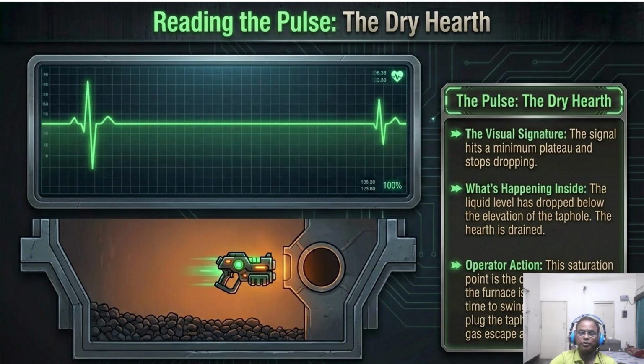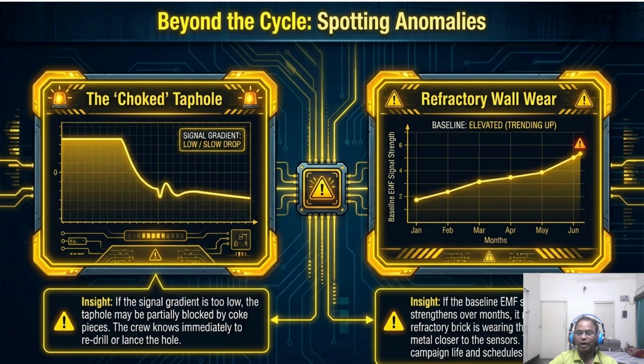But the benefits of this system go beyond just liquid level. We can also track the health of the furnace. Now we can also use EMF magnitude to monitor the refractory erosion. There is an empirical relationship. As the wall gets thinner, the electrical resistance drops and the EMF magnitude increases. For example, if our baseline signal shifts from 5.3 to 8.2 millivolts at the same temperature, you can estimate that about 95 millimeters of refractory have been lost. Additionally, the Nernst equation allows us to relate these voltages to oxygen activity, also giving us a chemical thermometer to predict the silicon content of hot metal before it even leaves the furnace.